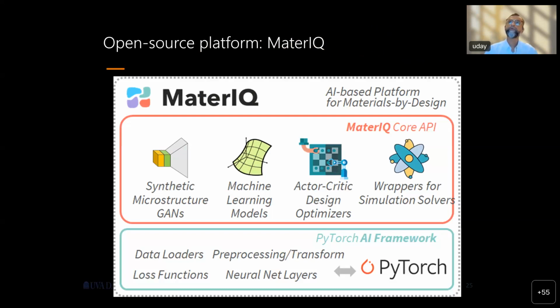In MaterIQ, which is again for materials by design, we have different components to the package. The first one is a synthetic microstructure generator. Because we don't have a large number of microstructural samples, we want to take archetypal samples that maybe you have one image for, but then generate an ensemble of samples so we can do statistical modeling of it. And then we can actually do DNS simulations on that ensemble. So that's the synthetic microstructure part.